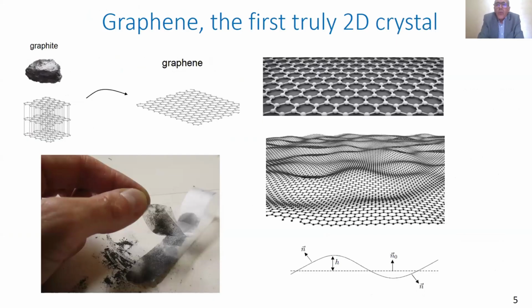I go back to the graphene, the first truly two-dimensional material. It is obtained from graphite, which is a layered bulk material. The distance between layers is enough to have van der Waals interaction, and the bending energy is low. That means that it is easy to exfoliate one monolayer, which is the graphene. And the structure of graphene is hexagonal, obtained by some simple mechanical exfoliation. But at larger scale, graphene has some ripples. This is to enhance its stability.